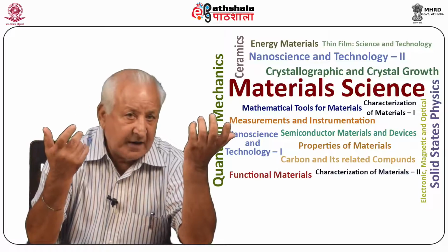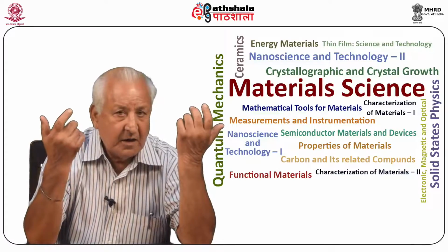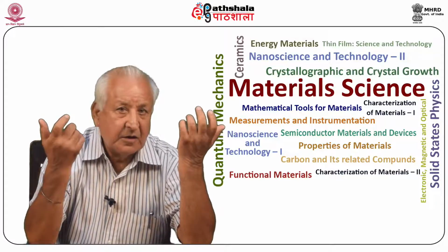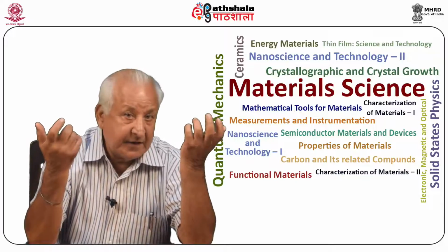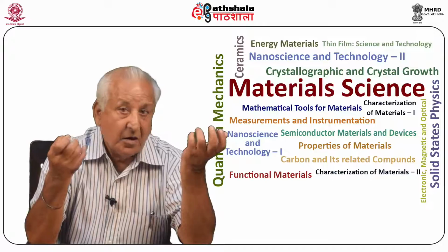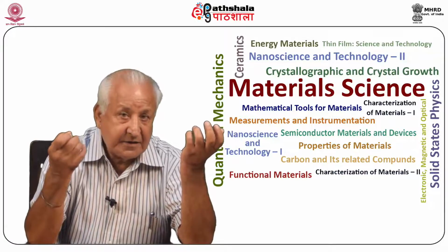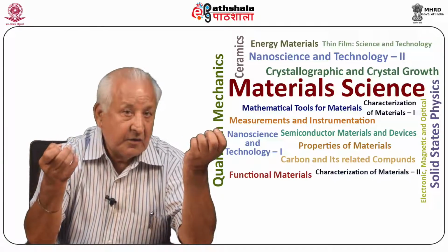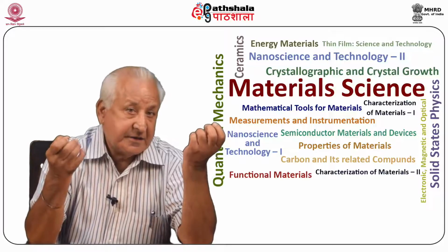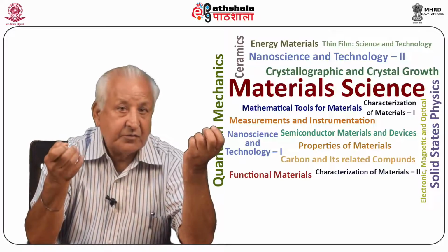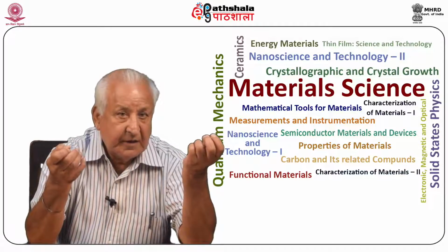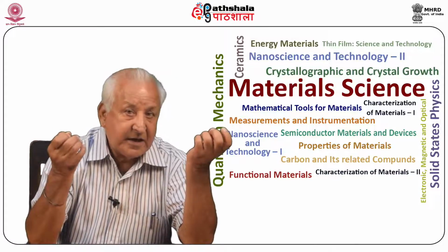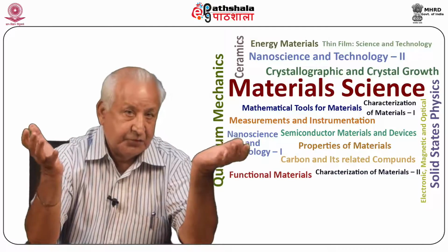is constructed by erecting vectors from an arbitrary origin within the crystal, perpendicular to the various crystallographic planes in the direct lattice, of length sigma HKL, given by sigma HKL equal to K upon d HKL, where K is a positive constant, usually taken as unity, but sometimes the X-ray wavelength lambda being used.